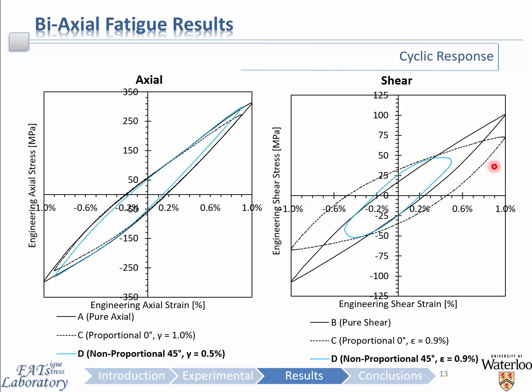Now, if we look at non-proportional loading at 45 degrees, it can also be observed that the axial response is still virtually identical to the previous cases, being the uniaxial and proportional biaxial. Now, the shear strain in this case was controlled to be at a lower strain level of 0.5%, as seen in the figure right here. The reason for this is that this particular loading history is representative of the service loads for the actual component that we discussed in the motivation part of this presentation.